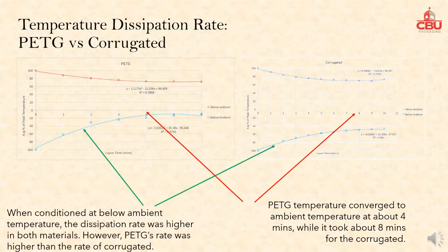This slide compares the temperature dissipation rates of PETG and corrugated. PETG temperature converged to ambient temperature at about 4 minutes, while it took about 8 minutes for the corrugated. When conditioned at below ambient temperature, the dissipation rate was higher in both materials. However, PETG's rate was higher than the rate of corrugated.